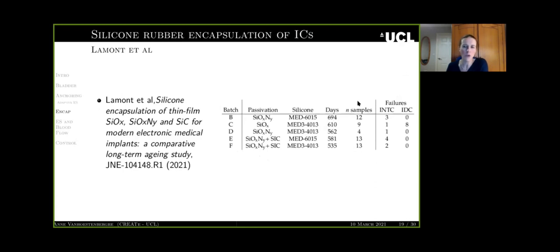Unfortunately, due to manufacturing issues, some of our samples are relatively small, but even in these small samples, we saw very few failures. INTC stands for interconnection failure. So that's, again, failures that are due to the manufacturing process. IDC failures, the failures that we were looking for, where the IDC, the interdigitated comb, shows us that there is a failure of the silicone rubber, only occurred in one batch, batch C.